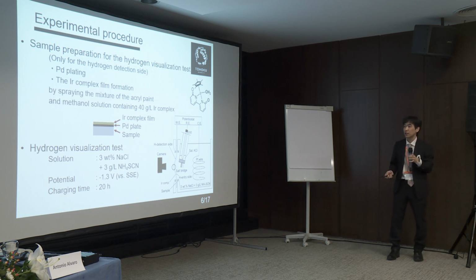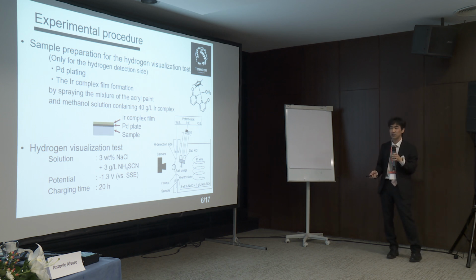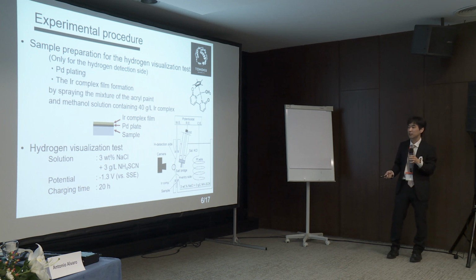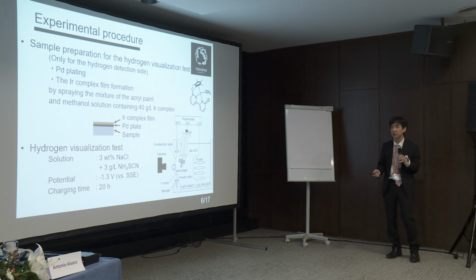Hydrogen was charged by the cathodic charging method, and the potential was set at minus 1.3 volts versus silver chloride electrode, and hydrogen was charged for 20 hours. The color of the iridium complex was observed by digital camera during the hydrogen charging every 5 minutes.